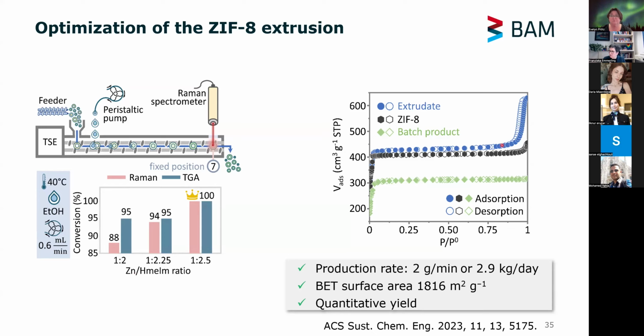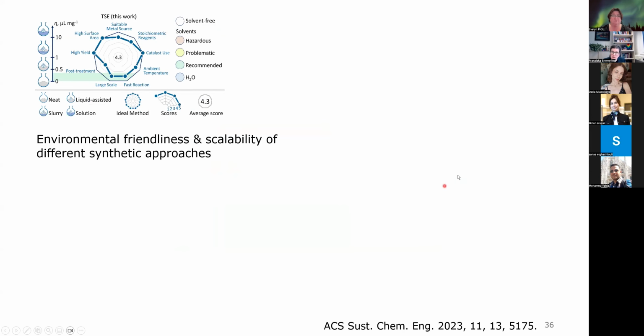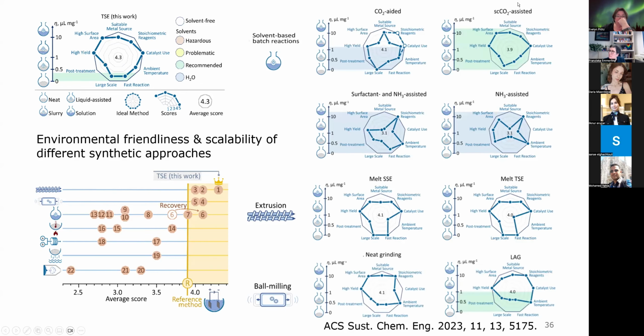Yeah, so that works. We get the material, but we also look into how green that is, and you can see here this radar chart where we compared a few other methods to our method, and we were optimizing a few aspects. Of course, you would like to have a high surface area. We want to use the reagents in a stoichiometric ratio, usually at ambient temperature, avoid critical solvents, and so on. And then you can see that's a longer comparison, and within our variables, our method seems to be one of the best, also better than some electrochemical methods, for instance.